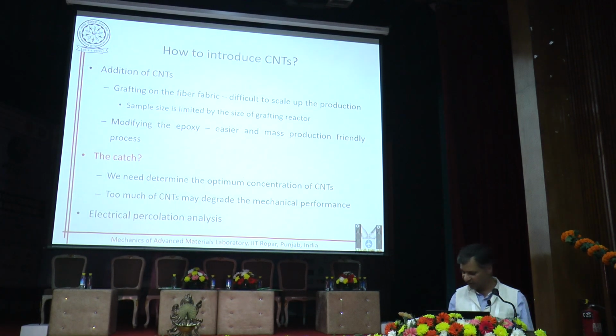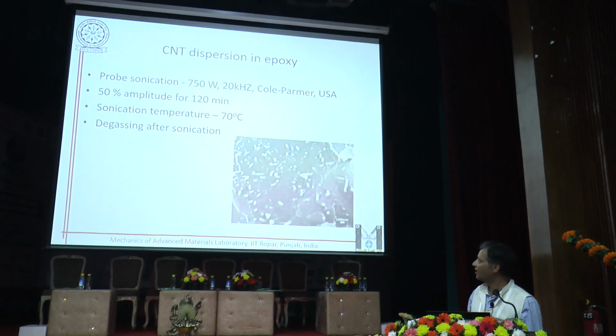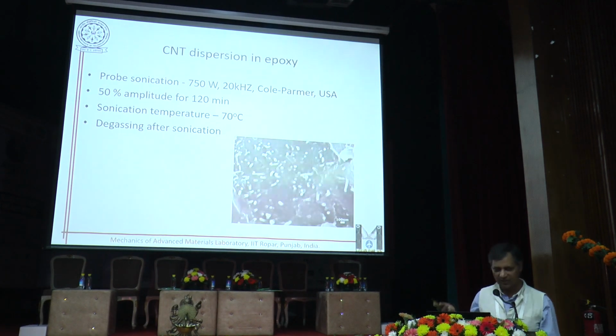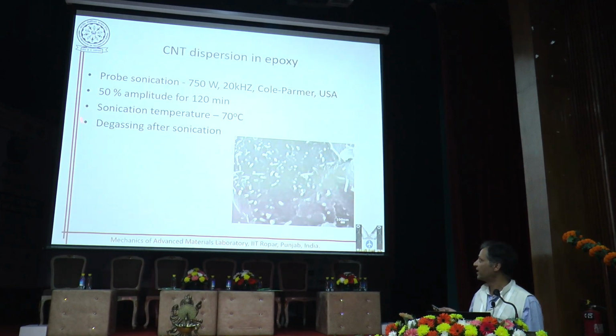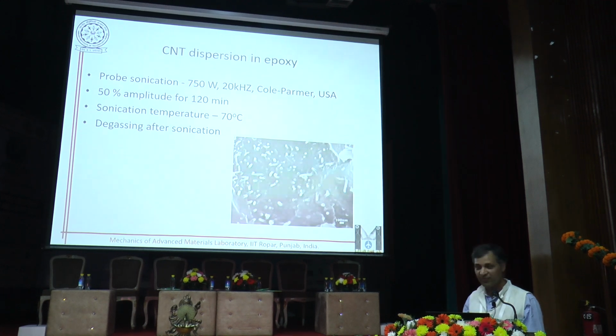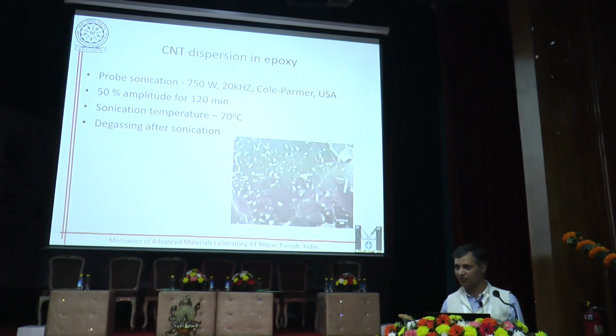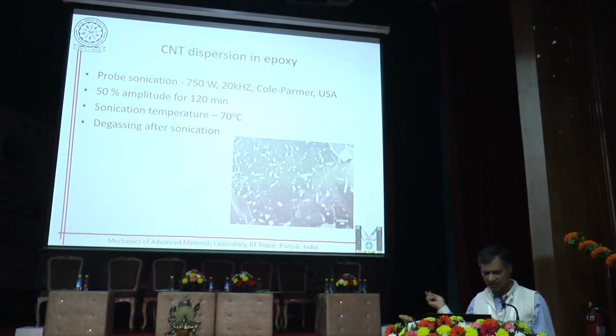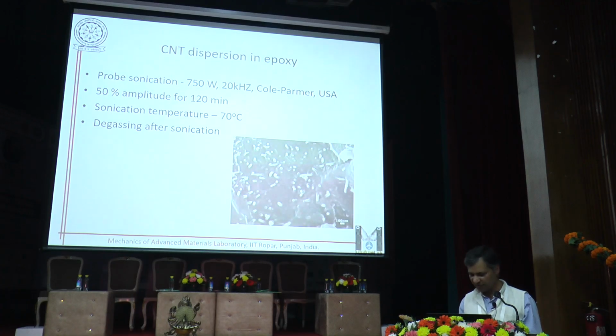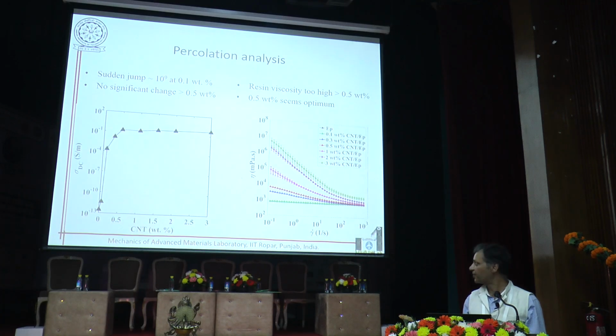Of course, there is a lot of theoretical framework that I am not going too much into. But after doing some theoretical calculation, we came up with a concentration of about 0.58%, and then we verified it with experiment. So we dispersed the CNTs into epoxy using probe sonication. Here are the parameters, and they are nicely dispersed across the whole volume. And then we compared the properties. So this is the DC conductivity and this is the viscosity.